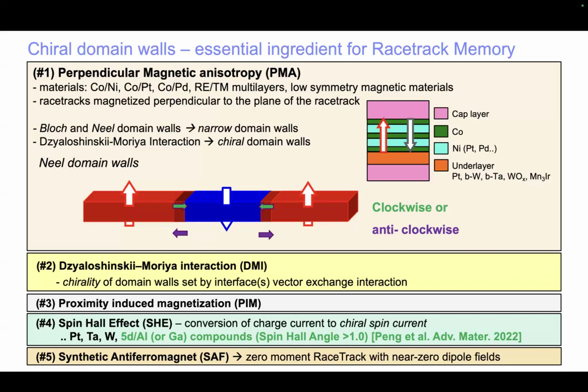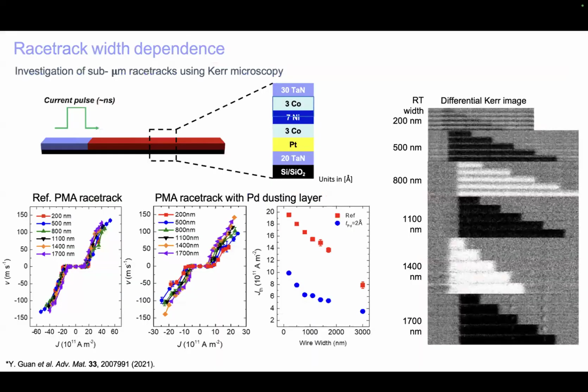And I'm not going to discuss, there's also a very important proximity-induced magnetization in the platinum layer, for example. The spin Hall effect I'll briefly mention, and the synthetic antiferromagnet I already mentioned. We have to design the magnetization everywhere in the racetrack to go to zero to avoid stray fields that cause significant interactions. So then, briefly, as shown here, we could use optical techniques using white light, long wavelengths, effectively to monitor the domain wall motion, even in racetracks that are only 200 nanometers wide.